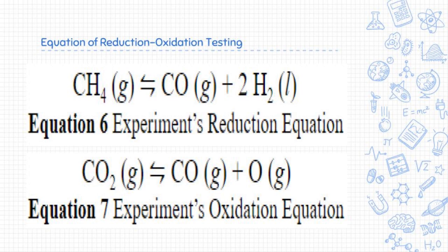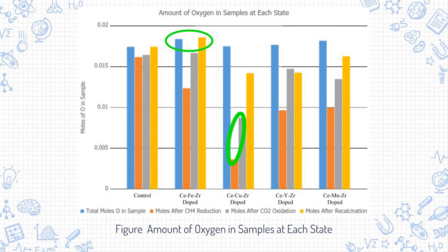As you can see on this bar graph, we have the control, iron, copper, yttrium, and manganese doubly doped membranes. The blue bar is the initial oxygen in moles, the orange is after methane passed, the gray is after carbon dioxide passed, the yellow is after the membrane was recalcinated. The general trend has the methane reduce the moles of oxygen, while carbon dioxide and recalcination increases the number of moles.